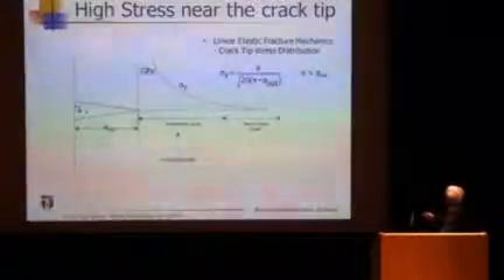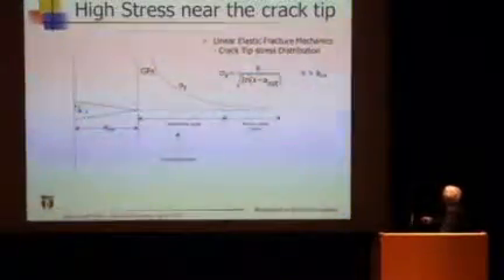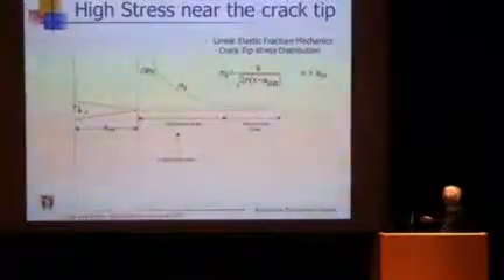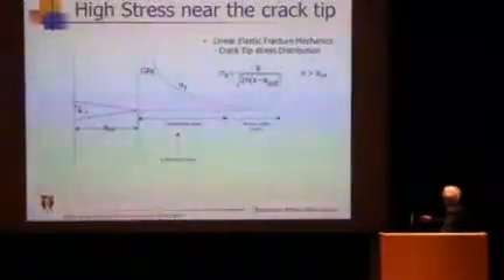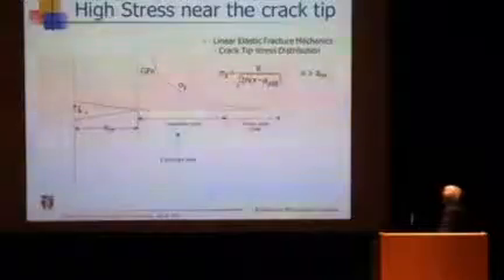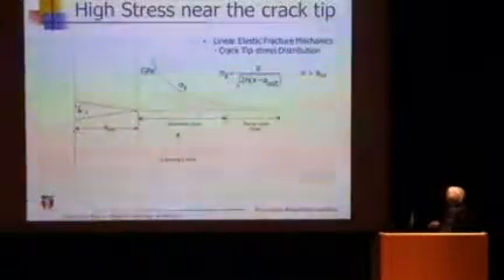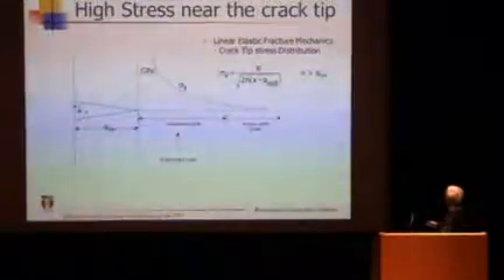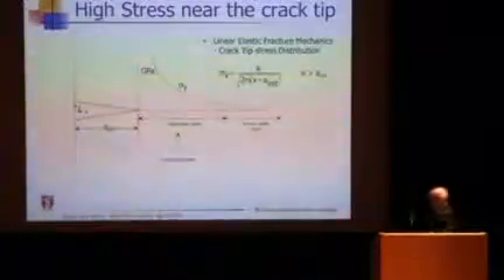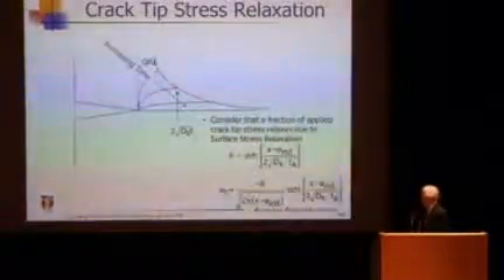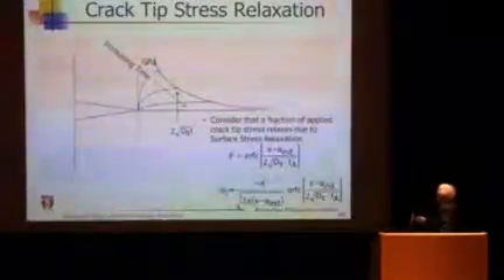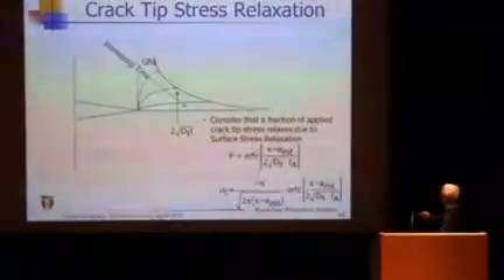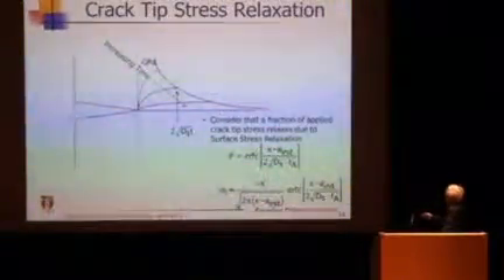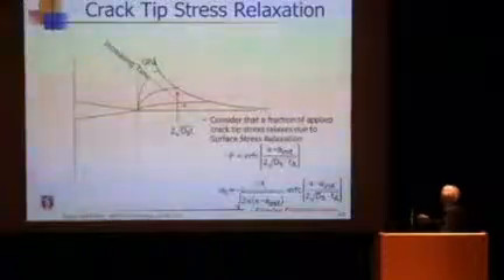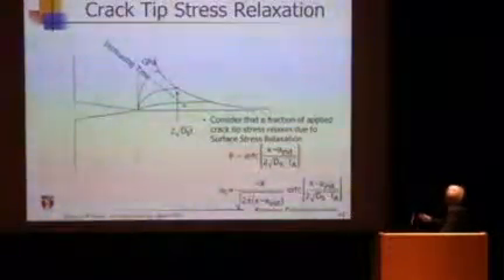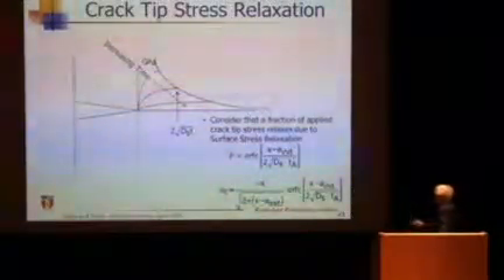Very high stress. This is the infinity. And this is the crack tip. And this is extremely high stress unless there's plastic deformation. Now, if you hold at a lower K value, this crack will not grow, or very little growth. And then there's a moisture effect. That stress is relaxing, with time going this way, this way. This is the diffusion control. So that would be propagating with the square root of time.